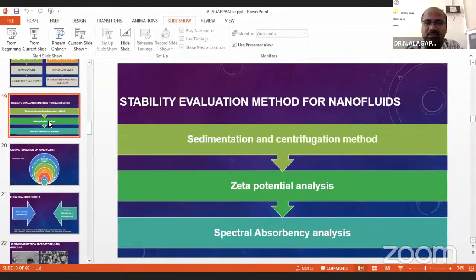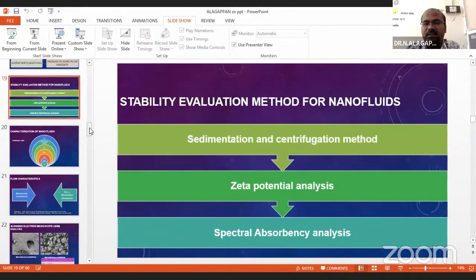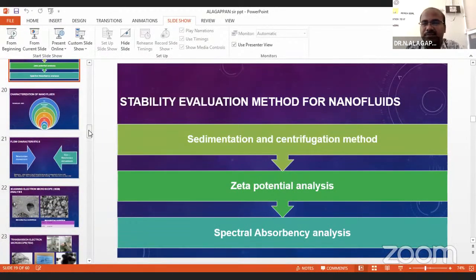Next slide. So stability evaluation method. There are 3 kinds of methods available. One is sedimentation and centrifugation method, then zeta potential analysis, and spectral absorbency analysis. So these are the 3 methods to check how your nanofluid is stabilized. Using the stability method itself, you know how many days your particles will be stable. So for example, 45 days, 60 days; you see cerium oxide is stable, which we analyze by means of zeta potential analysis. Next slide, sir.